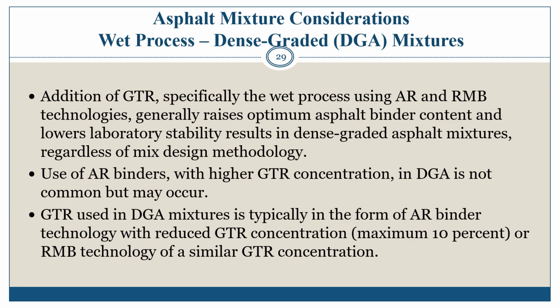Asphalt mixture considerations for wet process dense graded mixtures. The three common mix design methods, Marshall, Hveem, and Superpave, have been used to design dense graded mixtures with GTR modified binders. In dense graded mixtures, GTR modified binders generally increase optimum binder content and lower laboratory stability compared to conventional asphalt dense graded mixtures. This is generally a result of AR binder, or in the case of RMB, having a higher viscosity relative to conventional asphalt binder, preventing close packing of the aggregate, thereby needing more binder to get the same level of voids in the total mixture, or VTM.